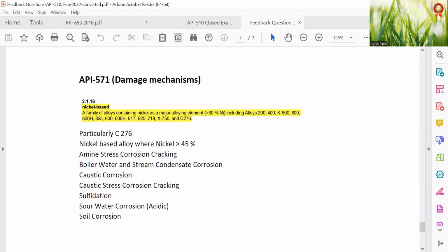API 571 damage mechanism, nickel based. A family of alloys containing nickel as the major alloying element, greater than 30% nickel, including alloys 200, 400, K500, 800, 800H, 825, 600, 600H, 617, 625, 718, X750 and C276, particularly C276, a nickel based alloy where nickel is greater than 45%. Amine stress corrosion cracking, boiler water and steam condensate corrosion, caustic stress corrosion cracking, sulfidation, sour water corrosion, acidic, soil corrosion.